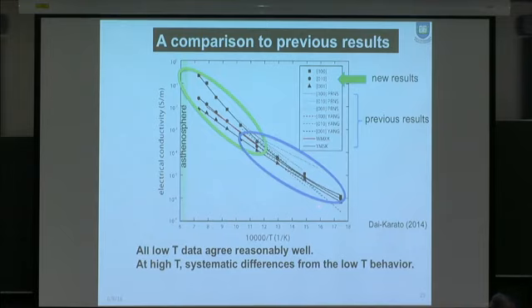One is that the slope is different, which means the activation energy is different, a new mechanism is operating. Another important observation is that in the low temperature range, anisotropy is almost 0, very isotropic, but at high temperatures, anisotropy is very strong. So therefore, the extrapolation of the laboratory conductivity data from the low temperature regime to the high temperature of the asthenosphere here is not justifiable.